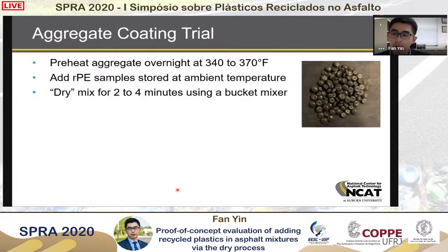The first thing we did is what we consider the aggregate coating trial. This is kind of like trying to simulate the research finding reported from India. So what we did here in the lab is we preheat those aggregates overnight at a very high temperature, like 340 to 370 degrees Fahrenheit. I mean, that's the typical mixing temperature that we have been using. And then we're going to add those PE pellets into the aggregate. But those plastic pellets were not preheated. So they were stored at room temperature, and they were just dropped into the bucket with hot aggregates.